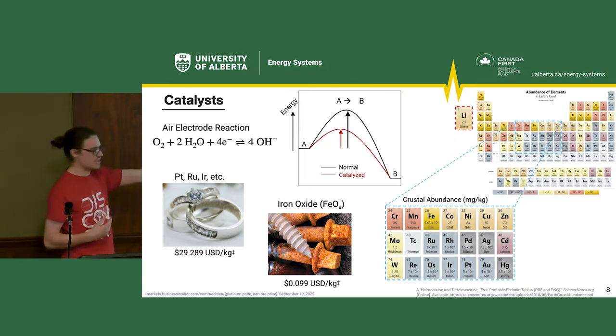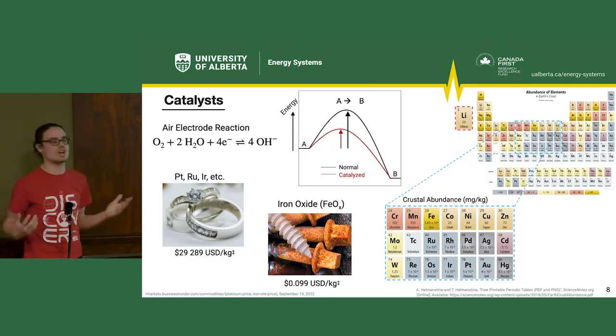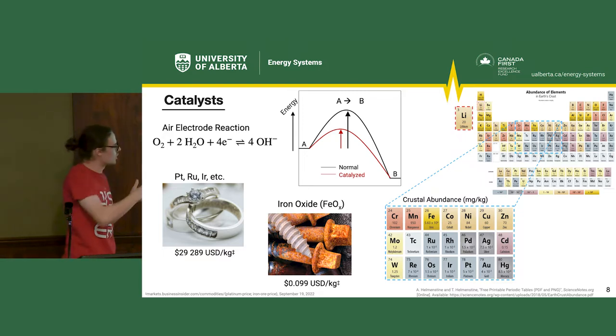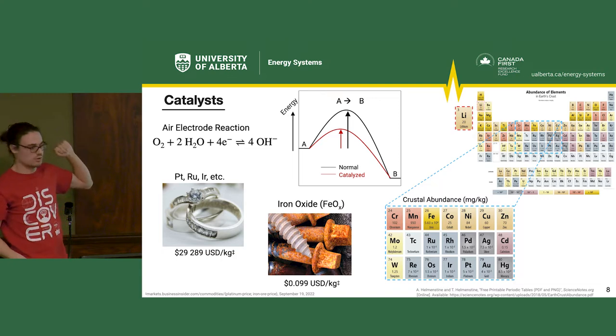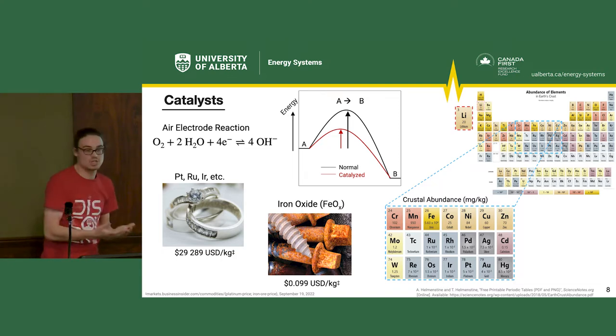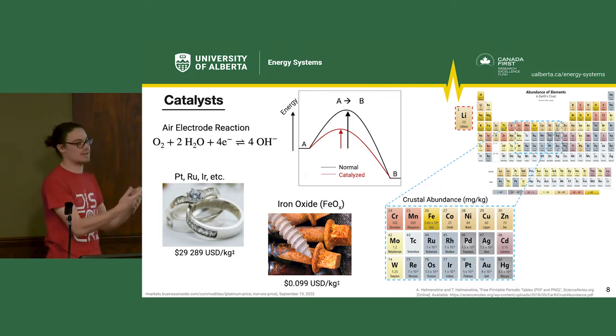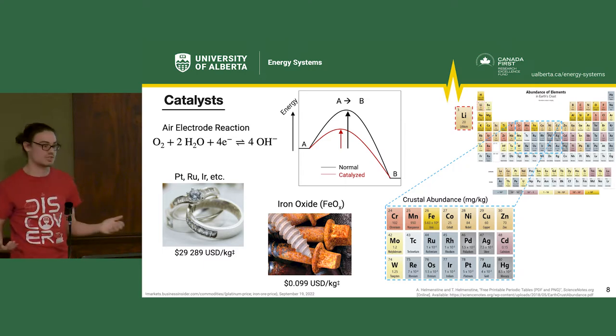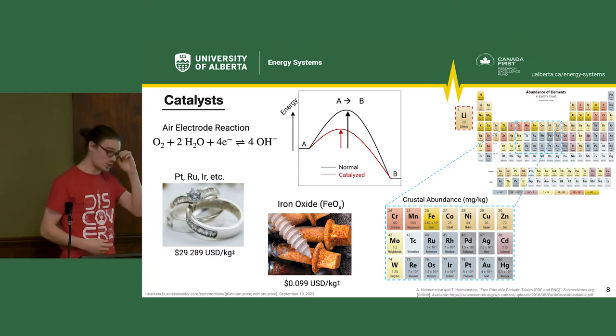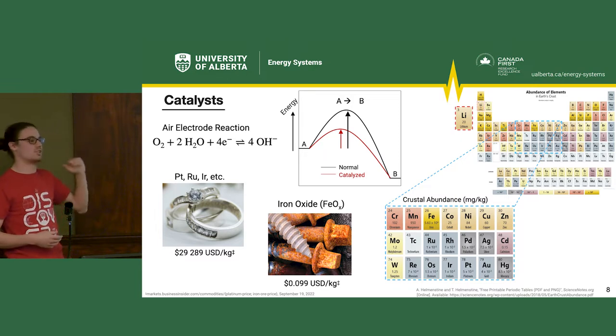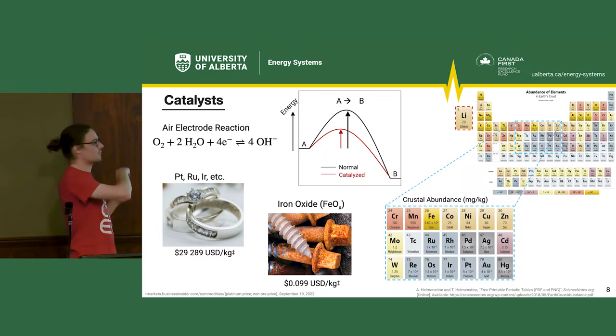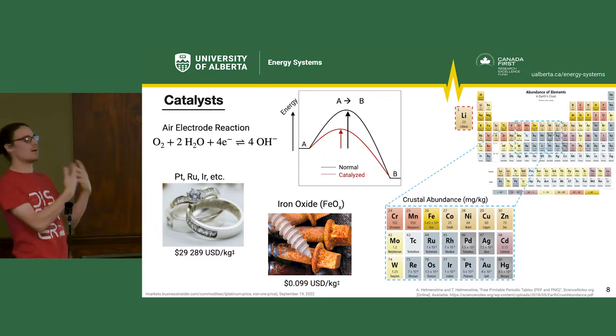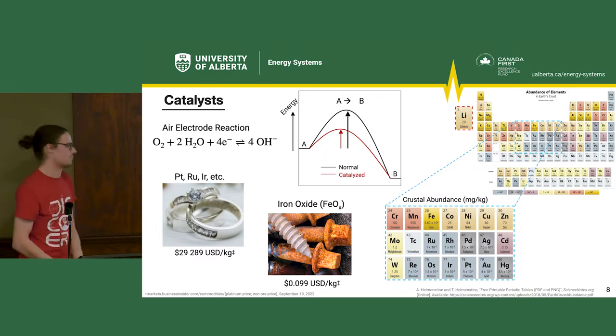And if you want to proceed in that reaction, we got to go over an energy hump. You can see there on the curve, right? There's an energy barrier. And so that excess energy we need to add to exceed that barrier kind of gets lost. That's where we lose efficiency values. If I can add a catalyst though, the right catalyst, we can reduce that energy barrier, that hump. And so then we can have less energy required to get over the hump and therefore a better efficiency.